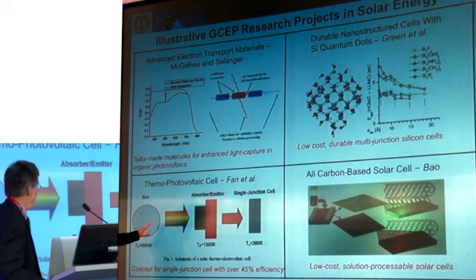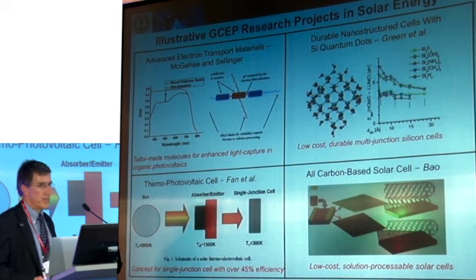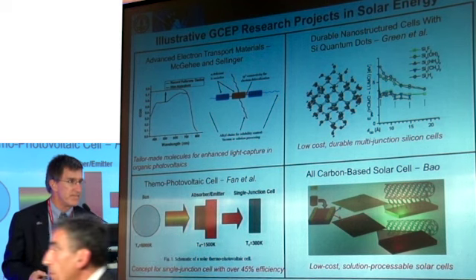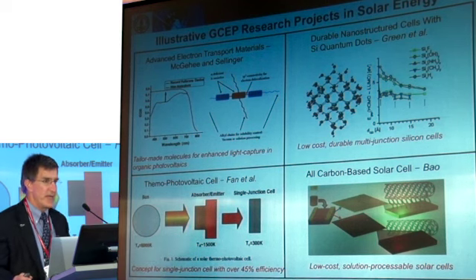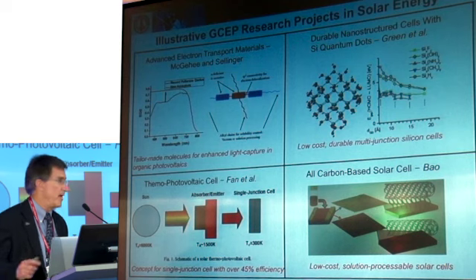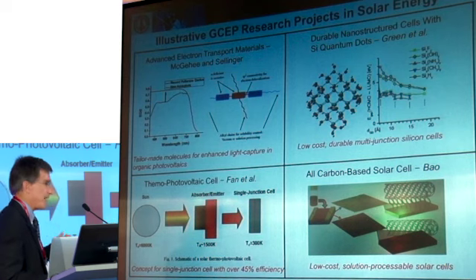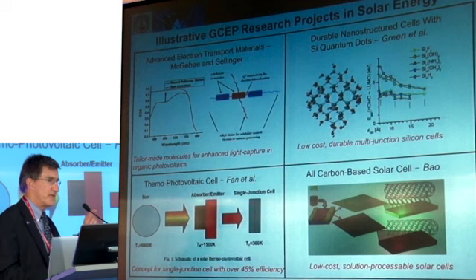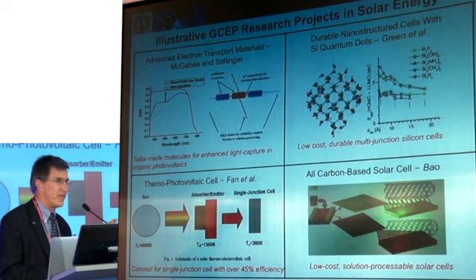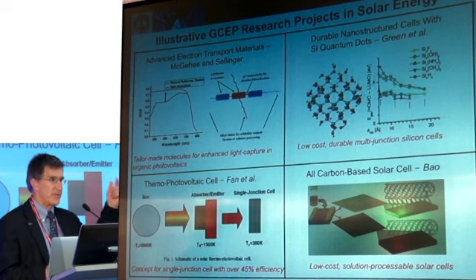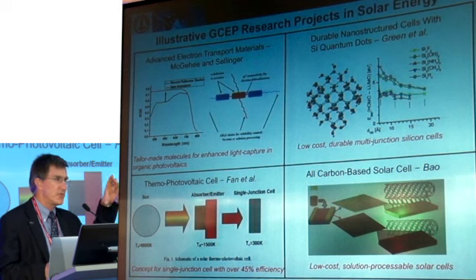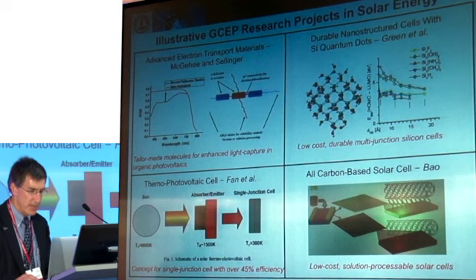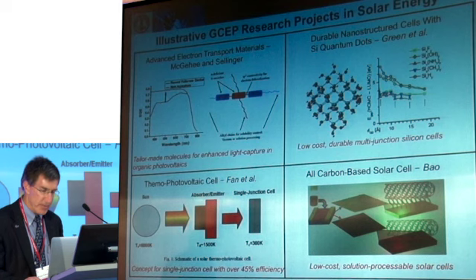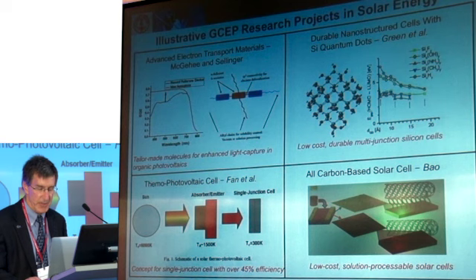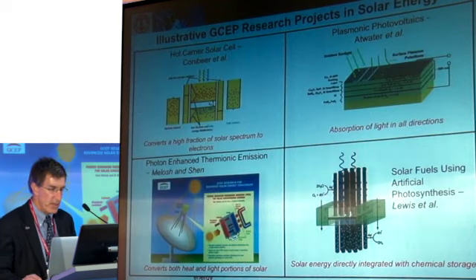You have light coming in causing heat, so you have a broadband absorption, and then a re-emission into a narrow band. And then you can have your semiconductor so that the light that's emitted has just enough energy to excite a carrier from the valence to the conduction band, so you don't lose so much in that relaxation process. And then she also mentioned the recent demonstration of an all-carbon-based solar cell, keeping to Earth-abundant materials.